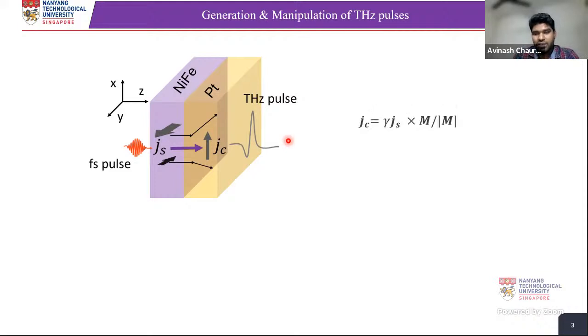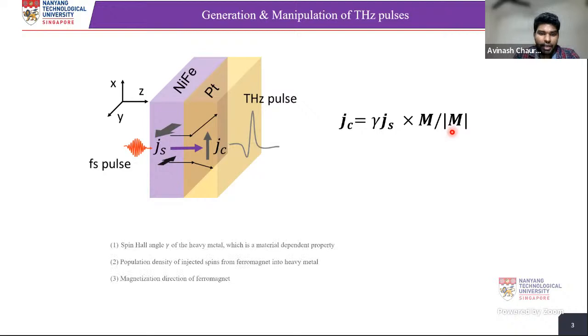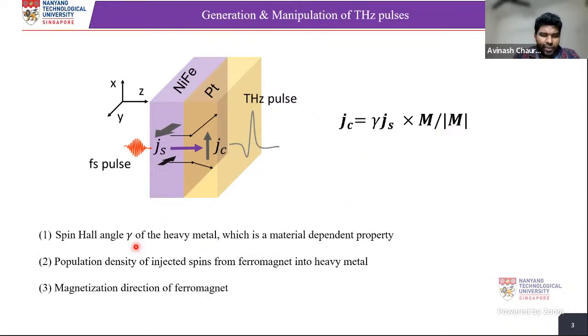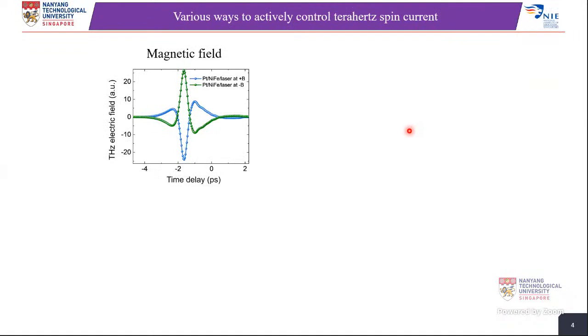The charge current is defined as J_C equals gamma J_S cross M by |M|, where gamma is the spin Hall angle of the material. By changing the material, like the heavy metal, we can control the charge current, and also if we change the fluence, we can control it. It also depends on the magnetization direction of the ferromagnet. So by these parameters, we can control it based on this equation.